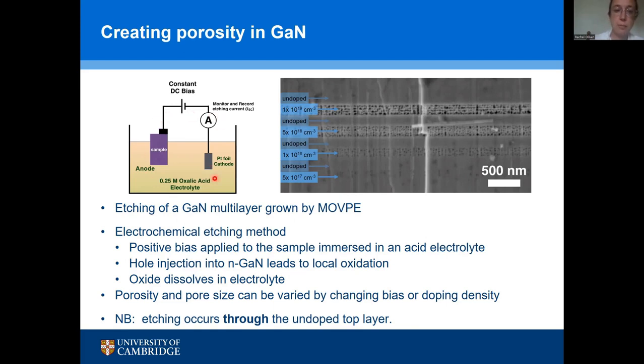And what we're doing is applying a positive bias to our sample, and that's leading to hole injection into the N-type gallium nitride, and those holes essentially catalyze oxidation of gallium nitride, and the oxide then dissolves in the electrolyte to leave behind pores. We can change the porosity by changing the bias we apply to the sample, or by changing the doping density.